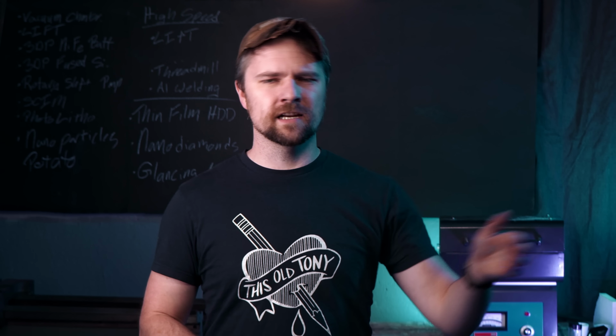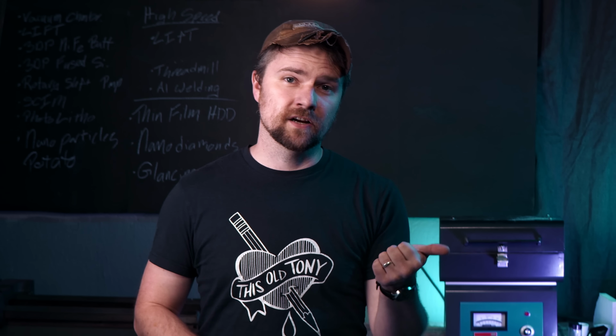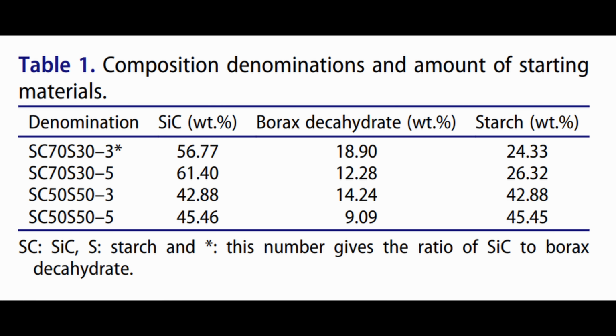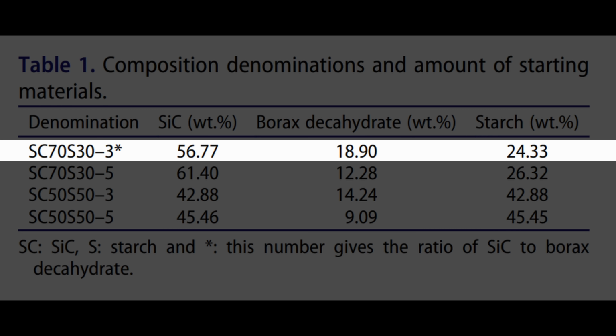A lot of the paper was about the porosity of these parts, and so they have a lot of different combinations of silicon carbide, starch, and borax to see how that affects the pores. I tried a few of them and they seemed to work, so I mostly focused on one sample just to simplify my life and really dial in that procedure for one of the recipes. The protocol itself is super straightforward.